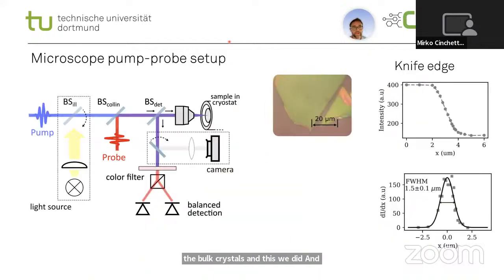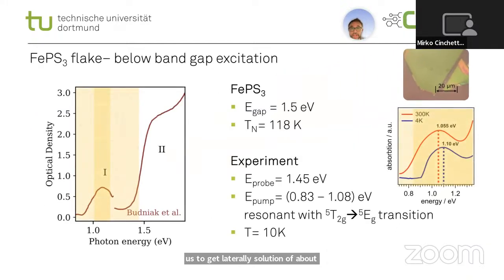And then if we want to study them in our setup, we also have to implement some kind of microscopy. So we use this kind of microscope objective that allows us to get a lateral resolution of about 1.5 microns. So then the experiments are done by pumping the system below the band gap, with a photon energy in the range between 0.83 and 1.08 electron volt, and probing with a photon energy which is slightly below the band gap.